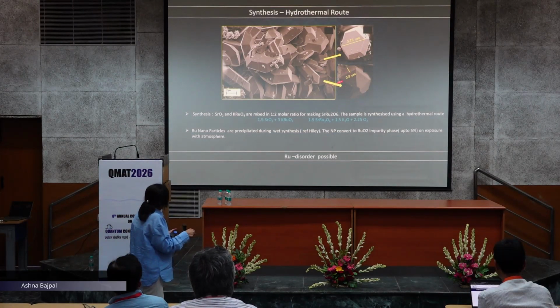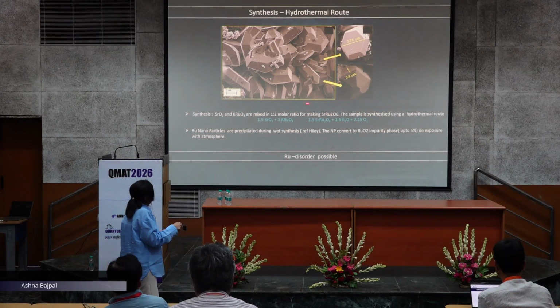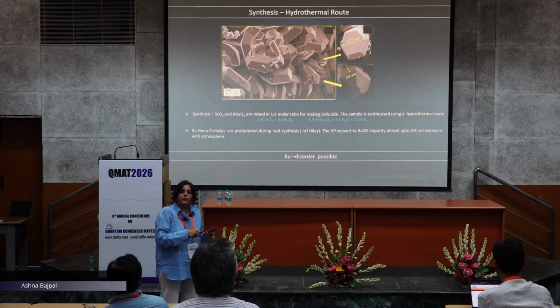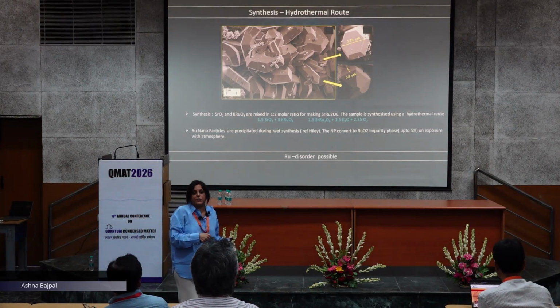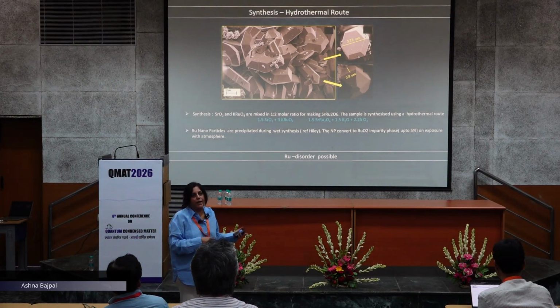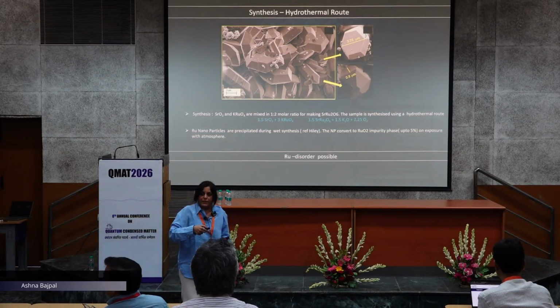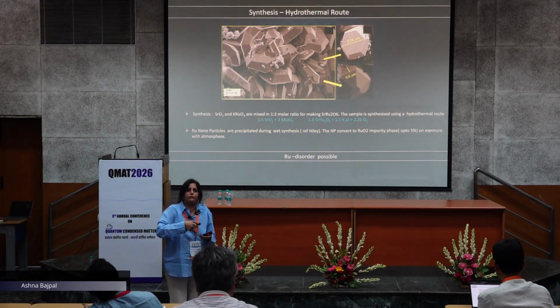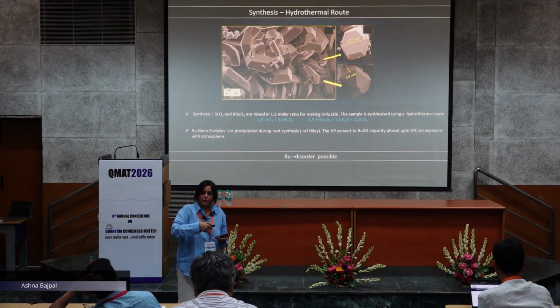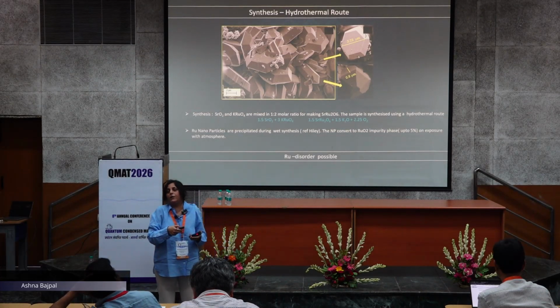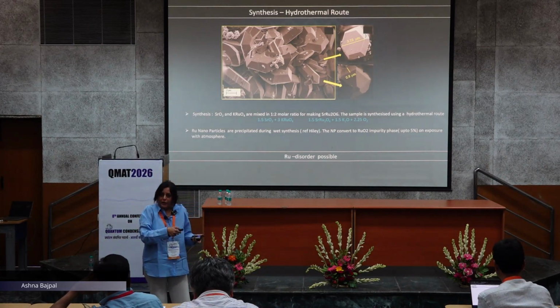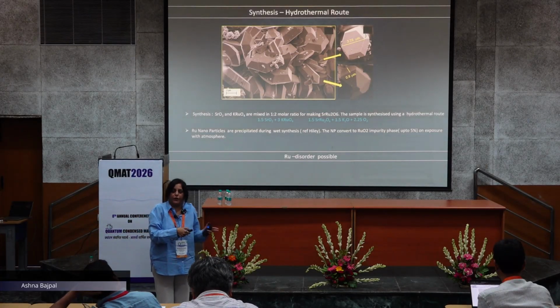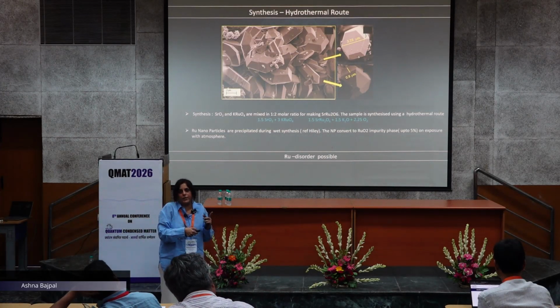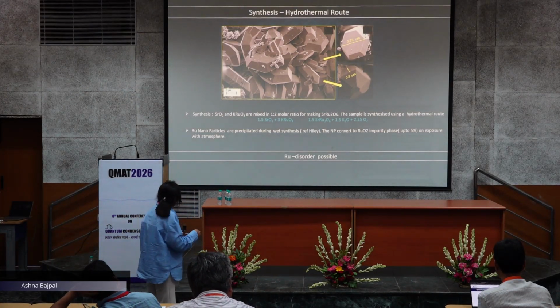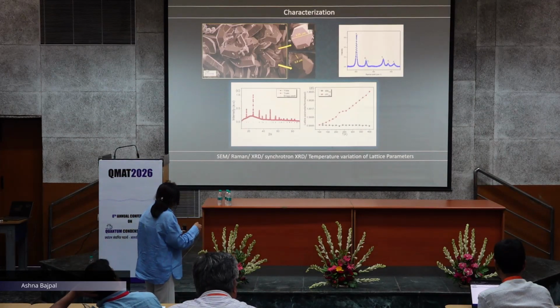One thing which I would just say is that Ru disorder is a possibility which is inherent to the synthesis route. Even the first group who reported this compound way back in 2015 found a little, 2 to 5%, RuO2 impurity, which basically comes from the precipitation of Ru metal, which turns into Ru oxide. Nevertheless, in whatever way, Ru disorder is a possibility. I would like to keep that in mind.